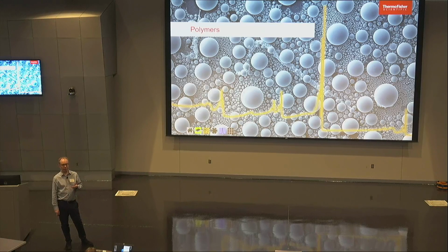Or there is a way of using that process I was talking about using the overlayer calculation. As you get to an interface, you use the overlayer calculator to determine the thickness of the layer as you sputter through it. And so you can work out how much etching relates to removing that material on the interface, looking at the layer below and the layer above, and you can use that to calculate the etch depth as well. But it always is a little bit of an approximation, and we tend to just put in an average depth. So the depth of the stack is probably correct. Of the individual layers, there will be an error on them just because of the nature of the sputtering process.